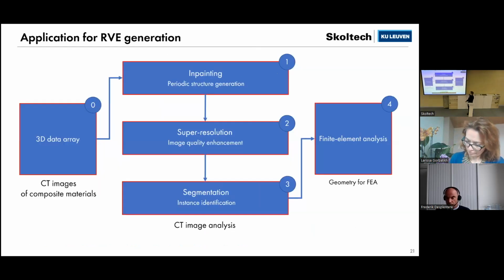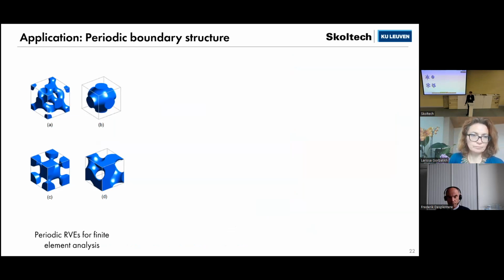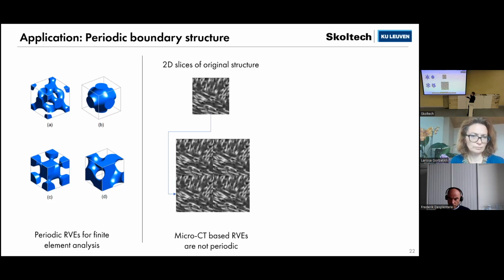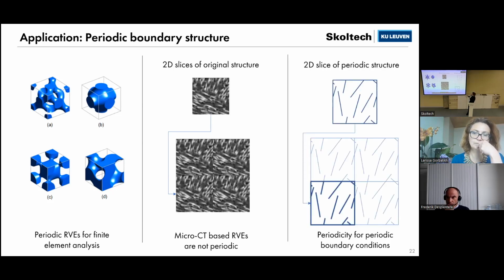And now I want to show you how it can be used for periodic boundary structure generation. Why we need periodicity in our representative volume elements. Here you can see examples of generated periodic RVEs, and you can see how it's periodic, and researchers are in favor of these kinds of periodic boundary conditions, and it gives better mechanical results. But when we use data-driven models, this cannot be the case, because, for example, here's our image, and when we connect it to each other in a periodic way, we have property jumps and so on, and we want to have a structure that will look like this.